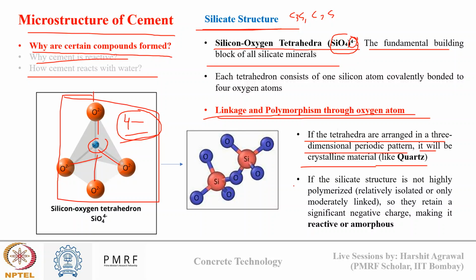However, if this silicate structure is not highly polymerized, not regular along all three directions, and remains relatively isolated or moderately linked, not completely linked, then it will have some negative charges which are still unbalanced. The presence of these unbalanced negative charges makes the silicate reactive and amorphous. Anything which is reactive is amorphous in nature, and anything which is not reactive is crystalline in nature. Sand is also composed of silica, but it is not reactive because it has a 3D structure of silicate. The silica tetrahedra are arranged in three-dimensional space. This polymerization is 3D in nature, that's why it is a crystalline material.